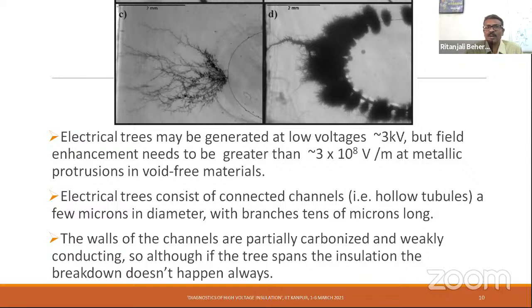That is one of the important reasons why even after the tree branches reach the other end, the breakdown doesn't happen immediately. However, there are research reports that have come out in the last more than a decade, which started exploring the conductivity of the tree channels, which had shown that the trees, particularly in the AC, are mostly conducting in type. However, in the DC, it takes time. It's not that easily becoming conductive.